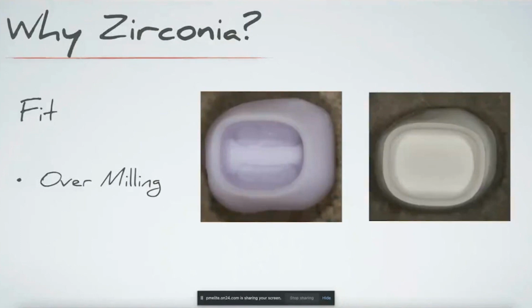The restoration on the right, again, at this point is roughly 28% bigger than its final restoration. It's also being milled with some very fine carbide burrs. We're not using diamonds when we're making zirconia restorations as we are with glass ceramics. The carbide burrs cut very clean, and because they have a smaller diameter, we're able to get a much more intimate fit of the intaglio surface to an abutment or to our prep or to whatever restoration we're performing.